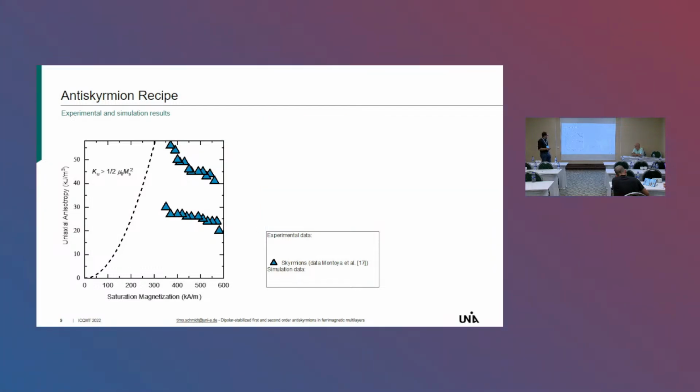And if we add our own, then we have here these coexisting anti-skyrmions and skyrmions in violet, and the samples which only had skyrmions in the blue squares, and also in-plane domains, basically here where the Ku value is just too low to get these out-of-plane things.